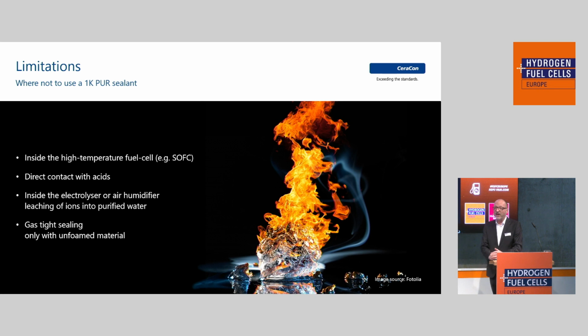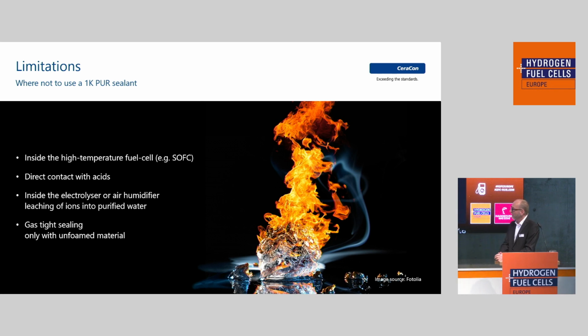It's not possible to get direct contact with acids. This is because of the chemistry of polyurethane. It is not suitable to use with acids, like you have in some electrolyzing facilities. And there is an issue with leaching of ions into purified water until now with the polyurethane foam. In every application you need this purified water, and there will be some ions leaching out of the polyurethane. If you want to have a gas sealing, so also for hydrogen, you can use this material in an unfoamed state. As a massive material, it's like a very strong rubber, and then you can use it.